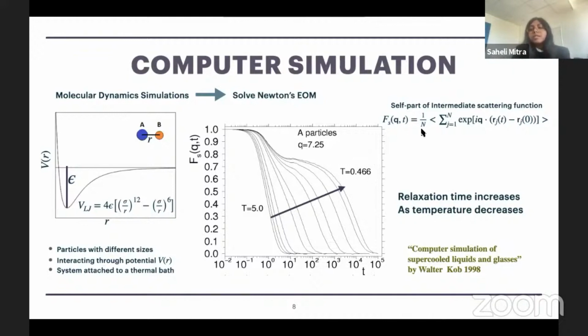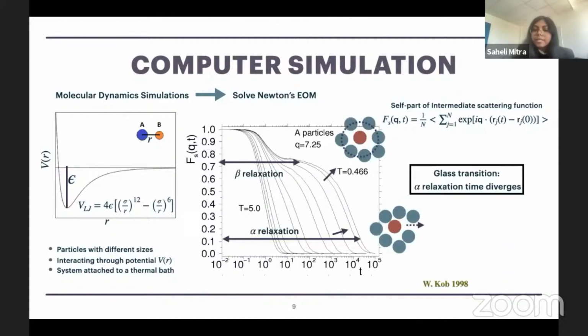Now we can compute the intermediate scattering function, which describes with reference to some initial time how a system relaxes. So for example, for high temperature, this relaxation will be very fast. And for low temperatures, it will take much more time to relax from the initial configuration. In fact, for glass forming materials, this kind of two-step relaxation at low temperature is a characteristic phenomenon. So in shorter time, the local degrees of freedom relax, which is known as the beta relaxation, and in long time, the degrees of freedom over larger length scale relax.